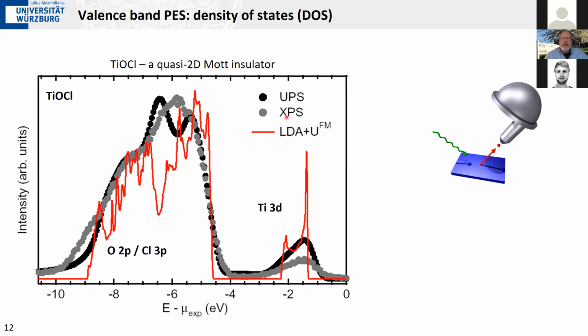As you can already see here from these two different spectra taken at different photon energies, there are some changes here. And these changes are due to matrix elements, or the transition probability for exciting an electron from the solid depends on A, the photon energy, and B, the orbital nature of the electrons that we excite. And so there are some certain variations in here. So you have always to be a little bit careful when you interpret such data. It's not the bare density of states, but it's weighted with the relative excitation cross sections. But overall, as you can see by the comparison here to a density functional type calculation, the agreement is quite good.